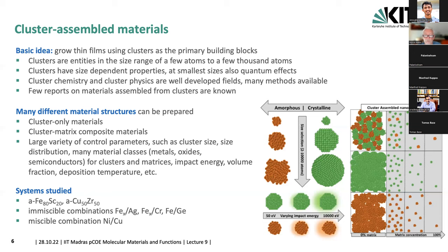So what we can do is, once we have the clusters, we can just deposit them one after the other and grow a three-dimensional arrangement of clusters on a substrate. That is what I call here cluster-only materials. We would only have clusters as building blocks and assemble them. In doing that, we would form, of course, interfaces between the clusters. And because we have a very large surface area in these clusters, it is not clear whether these structures would be stable. That's one thing which we have to study: whether, for example, if these clusters are crystalline, a nano or ultra-nanocrystalline cluster assembled material would be stable, or whether it would just continue to grow in size. I think that is a challenge which we have to look into.